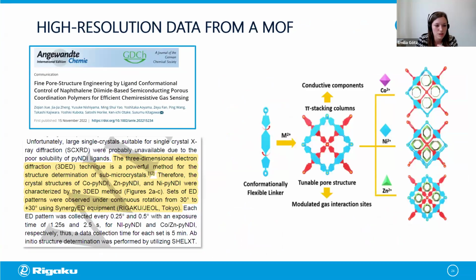Another structure with a high resolution of 0.65 angstrom was published in this paper by Xue et al. And in this case, it's not an inorganic one, but actually a MOF, or actually several MOF structures. So this really shows that we can also get high resolution data from these kinds of crystals and not just nicely diffracting inorganic ones.